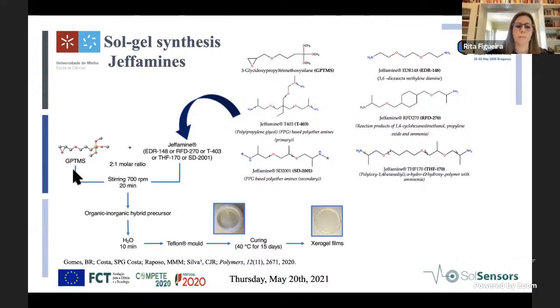We maintained always GPTMS, and we changed the jeffamine. We used jeffamine EDR 148, jeffamine T 403, jeffamine RFD 270, SD 2001, and THF 170. The difference between these jeffamines is the molecular weight, between SD 2001 and THF 170 and EDR 148. This one has a ramification and this one has an aliphatic ring in the middle. So you will see that this difference is reflected in the properties.